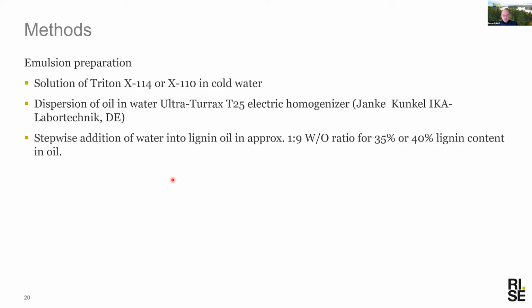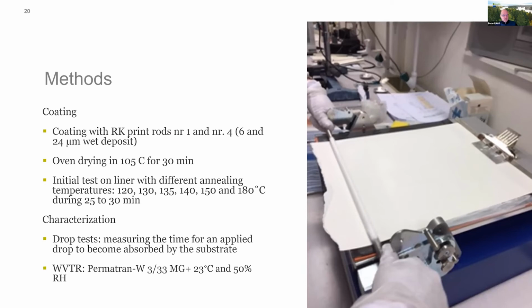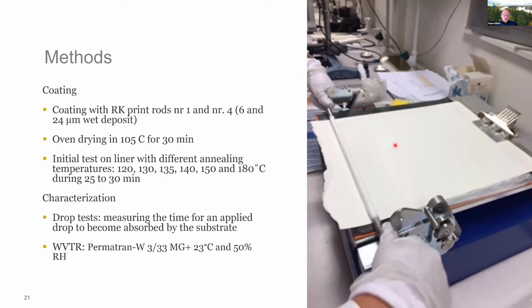As I said, what we would do is make a solution in cold water out of the surfactant, Triton X-114 or X-110. We would disperse the oil in a homogenizer with a quite high stirring rate, and we would stepwise add the water into the system here. We put a water in oil emulsion here. We did bend coatings, and dried them for 30 minutes first at 105 degrees, and then we had an extra annealing step at different temperatures and characterized it by putting a drop and observing how it would dissolve into the surface, but we also measured the water vapor transmission rate.